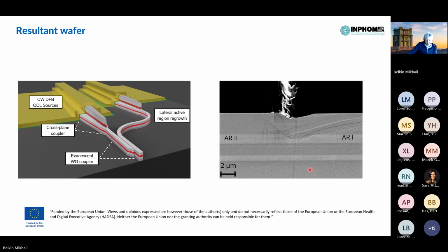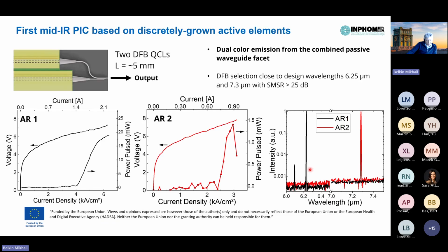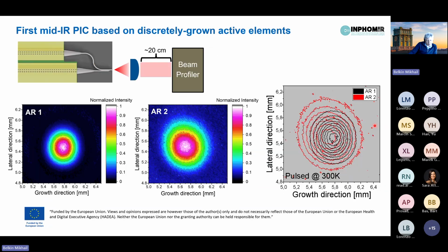This is how the wafer looks like. And this is the first demonstration actually of functional photonic integrated circuits in the mid-infrared spectral range with two distinct active regions integrated on the same platform. So some device operation at room temperature, and you could see some emission spectra targeting SO2 and NO2 gases. Also, the far field profile, since they're coming from the same facet, is well overlapped, and basically this shows the capability of this mid-IR photonic integration on InP.